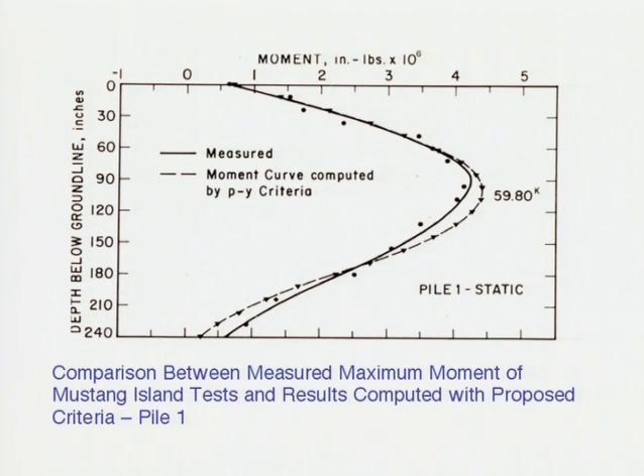So the integration and differentiation and the cross-plotting we did appeared to be working fairly well and gave us a pretty good agreement between calculated values using the PY curves we developed, the criteria, and the applied load. Notice that we put on this 24-inch pile, this is static loading, a fairly significant load.